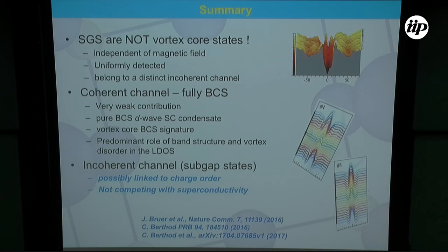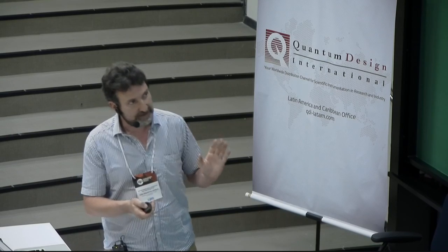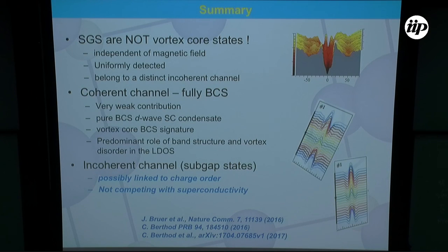So let me conclude. First, the take-home message is that these subgap states, finite energy states measured in YBCO, are not specifically connected and linked with the vortex cores. We assume that they belong to a distinct incoherent channel, probably together with some other spectroscopic features. Concerning the coherent channel, we see that it's fully BCS, D-wave. The contribution of this channel is of the order of 15% in the total current, which is quite weak. And this also explains why this zero bias anomaly in the cores is not emerging as it does in the case of S-wave superconductors.